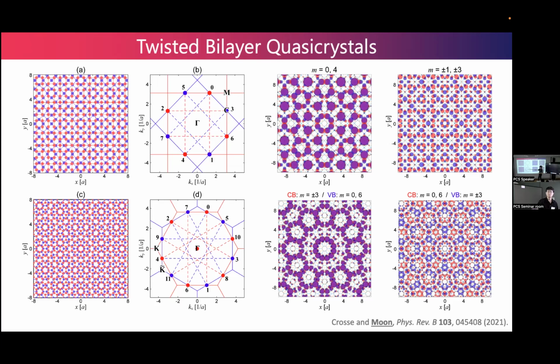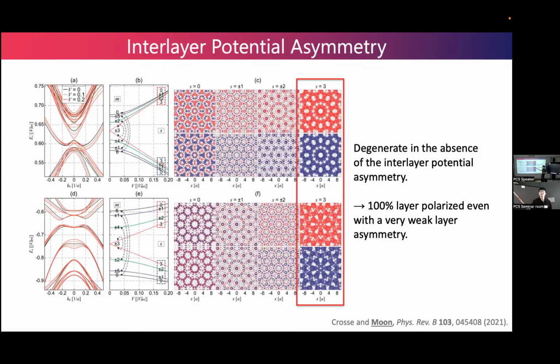And yeah, this is the real space lattice, and this is the nonlinear states involved in the calculation, the combination. So as you can see, the relative coordinate of red points with respect to the red Brillouin zone, and the relative coordinate of blue points with respect to the blue Brillouin zone. These states are all degenerate, and they are coupled by the reciprocal lattice vector of each layer. So they satisfy the momentum matching condition. If we apply interlayer potential asymmetry, most of the states still keep the mixing between two layers. However, the center states, which were originally degenerate, become completely layer polarized, even with a very weak layer asymmetry.